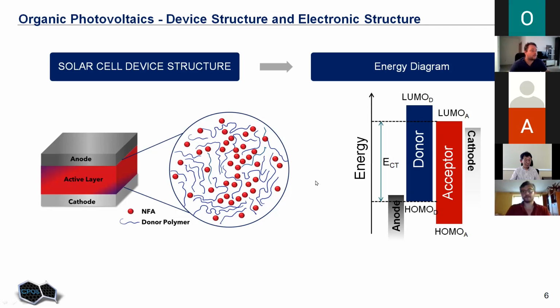So we cannot use just one organic semiconductor, for instance, this blue or red, because of the excitonic nature of photoexcited events in this semiconductor. Organic semiconductors possess very low dielectric constant. That means that electrostatic interaction between electron and hole is quite strong. And there is some binding energy of exciton, which cannot be compensated with thermal energy at normal temperature, at room temperature, common for operation of solar cells.